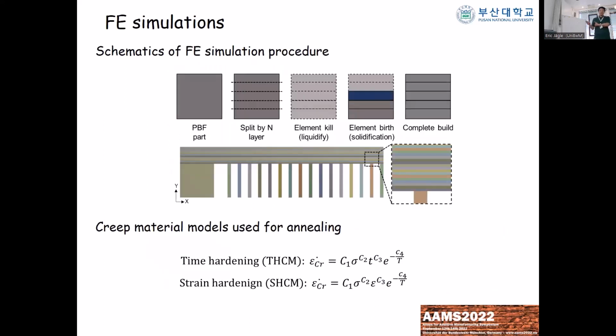This is our basic model, and I will not go into all the details of this, but basically it works like this. This is a finite element model, a structural analysis. Firstly, we deactivate all the powder part by considering the material as having zero or near-zero stiffness, so it's basically some kind of liquid. And then we activate the material one layer at a time. And then we artificially shrink the material by a defined amount.